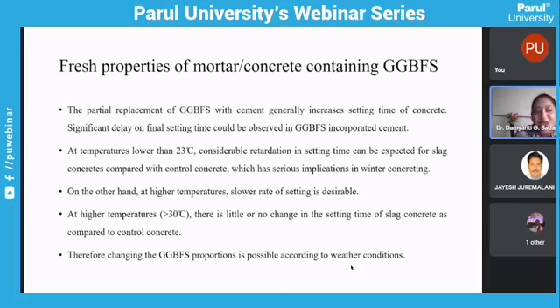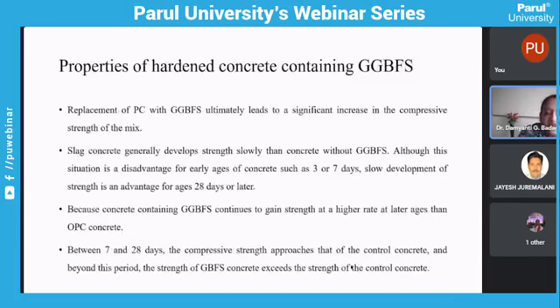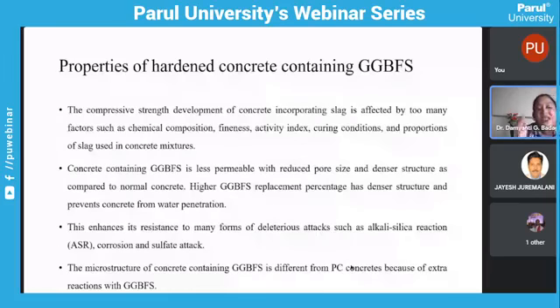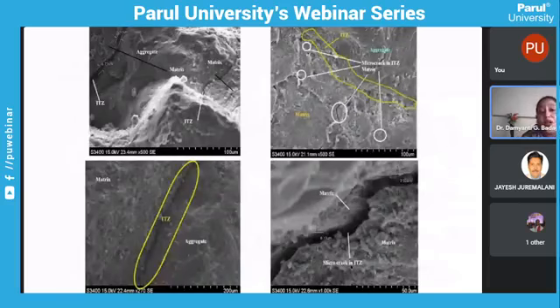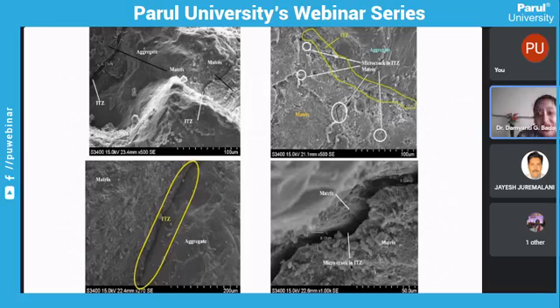For other materials, I am sharing the experience of other researchers and other literature, right? So after 3 days, 7 days, 28 days, 50 days, 60 days, 90 days, 120 days, and even till 180 days, after 6 months also, we got very good results.